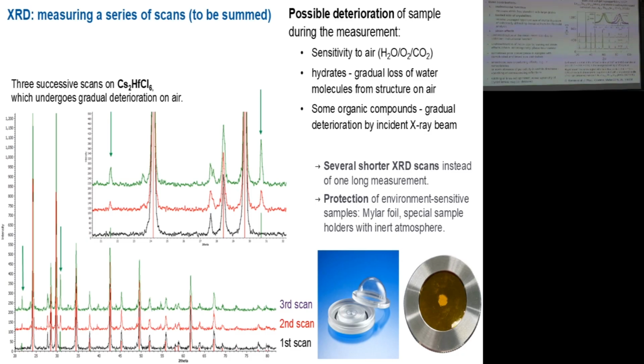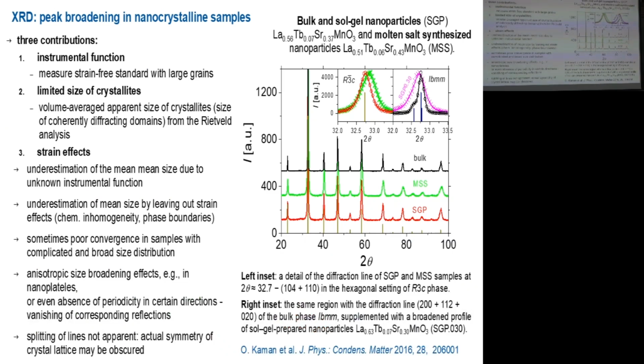So let's go to important issues. I mentioned that there is the phenomenon of line broadening, which is mostly related to the size of crystallites. However, there are 3 contributions in the line broadening. Generally and inevitably, there is all the time some contribution from your diffractometer. So there is also some instrumental broadening which you should determine.